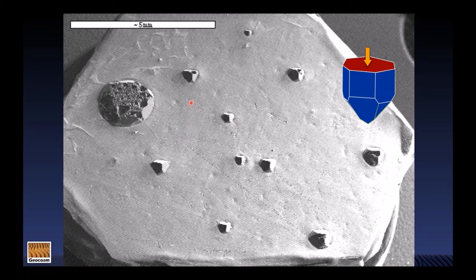And so if our hypothesis was correct, what we would have expected to see is if we looked edge onto this plate after a lot of time in the reactor, that the overgrowth that grew on this large hole should have grown further away from this plate compared to these overgrowths growing on the small holes. So let's see what happened.